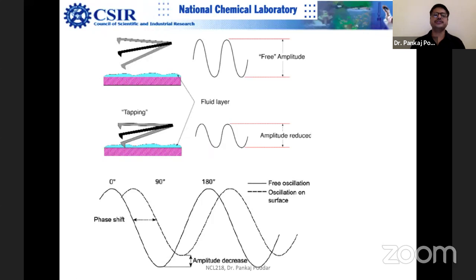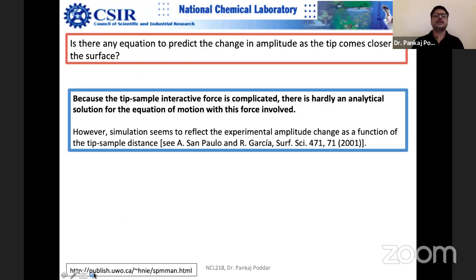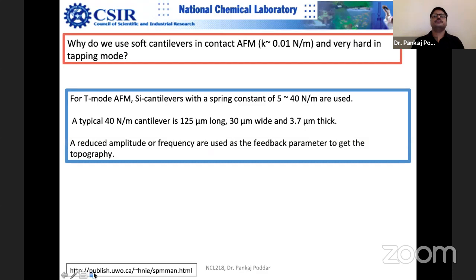So everything is changing. Now it is up to you, as I mentioned, that you can detect either amplitude or phase or frequency. It depends upon what kind of measurements you do. So normally we do not use soft cantilevers in tapping mode. We normally use hard cantilevers, bar shaped, and the spring constant is quite large, tens of Newton per meter.